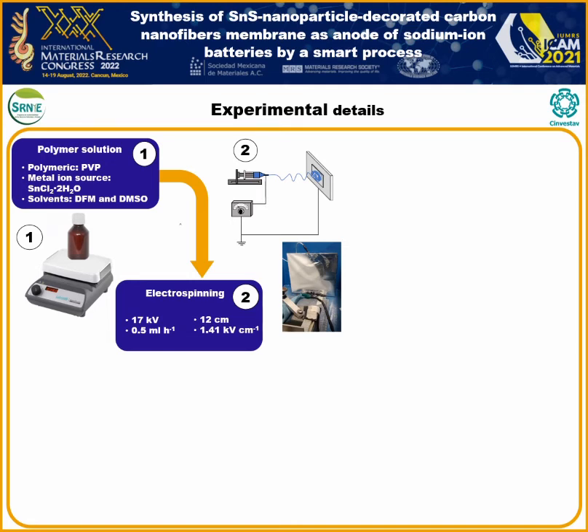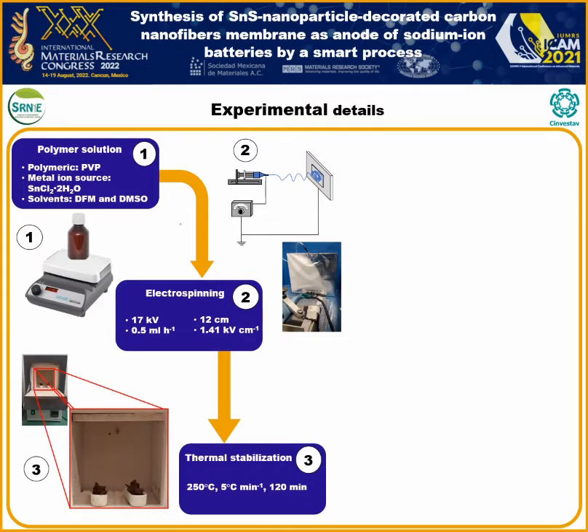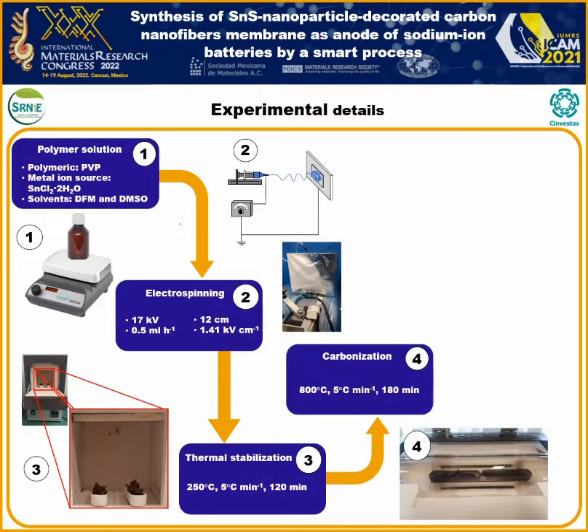The synthesis conditions were as follows: a distance of 12 cm between the cylinder and the collector, a voltage of 17 kV, and a flow rate of 0.5 ml per hour. Thereafter, the polymer nanofibers were stabilized at 250 Celsius for 2 hours in air and carbonized at 800 Celsius in an inert atmosphere for 3 hours with a heating rate of 5 Celsius per minute.